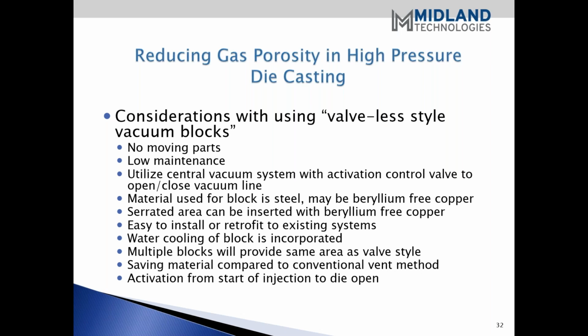Water cooling of the block is incorporated, and multiple blocks will provide the same area as a valve style. And you can save material compared to the conventional venting method as well, to save your metal. And the activation is from the start of injection to when the die opens. So you don't need to turn off your vacuum as soon as your shot is done. You can keep the vacuum on until you open up the die.